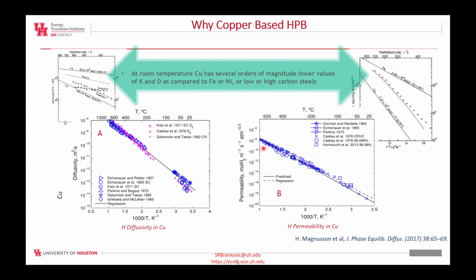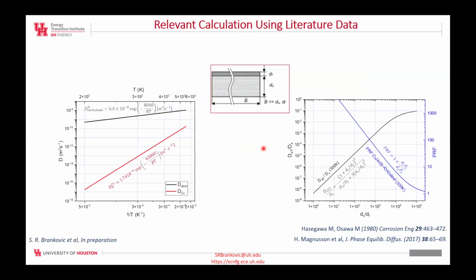So when we survey the literature for hydrogen permeation materials, we see that copper is identified as the one that has about several orders of magnitude lower solubility and diffusivity of hydrogen than in a regular iron or steel. Therefore, we can actually pretty well calculate it from the well-known data, the effect of copper thin film barrier coatings on hydrogen permeation through a steel using the literature data. And this is what we have done here.